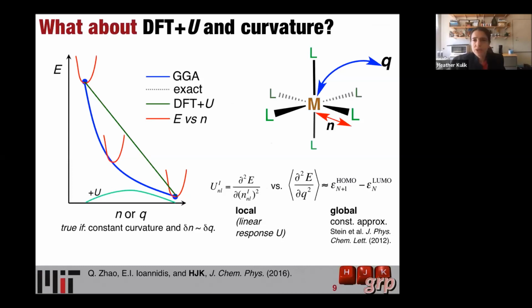what we usually say is that a U below 5 to 6 eV will have linear dependence, and I hinted at this, but I should have had a slide on this. Any property you predict will have a linear dependence on Hubbard U for moderate U values, say up to 6 eV. So you should know pretty quickly how much your property, say your band gap, is going to shift when you apply the Hubbard U and slowly increase.